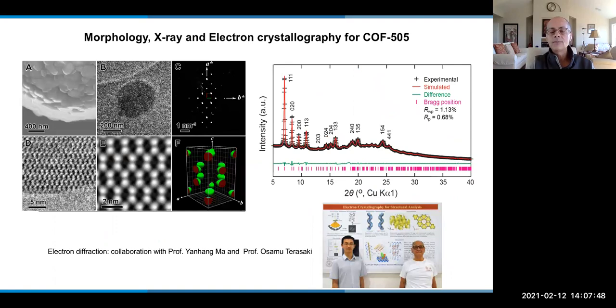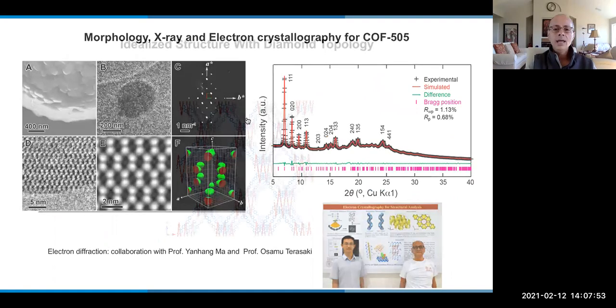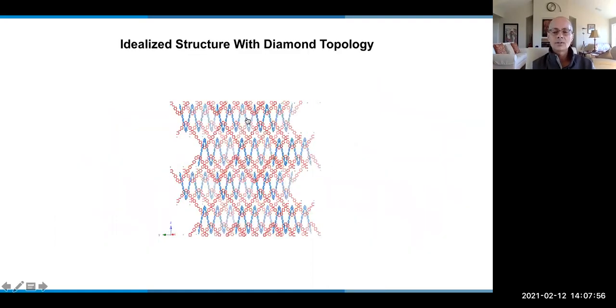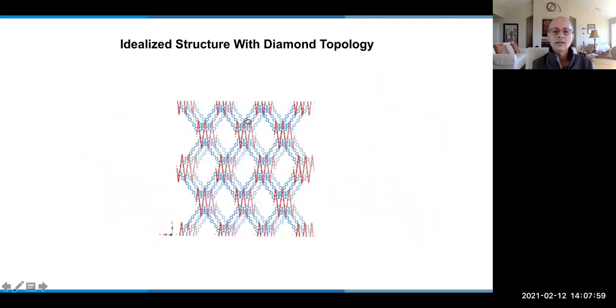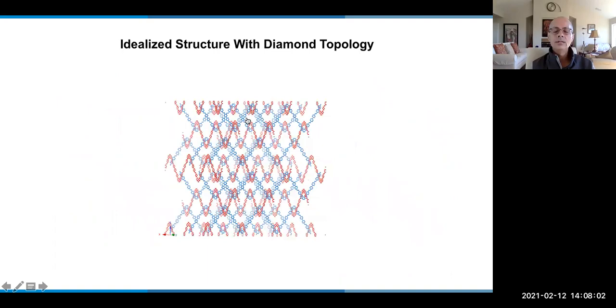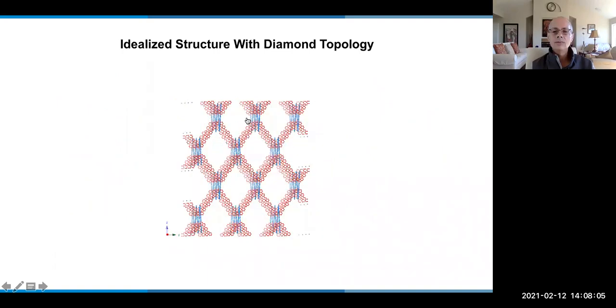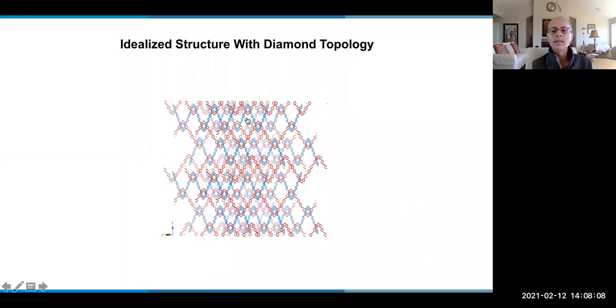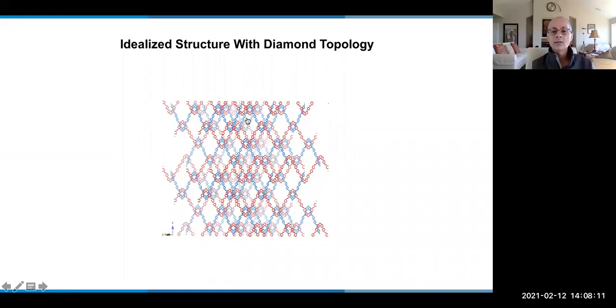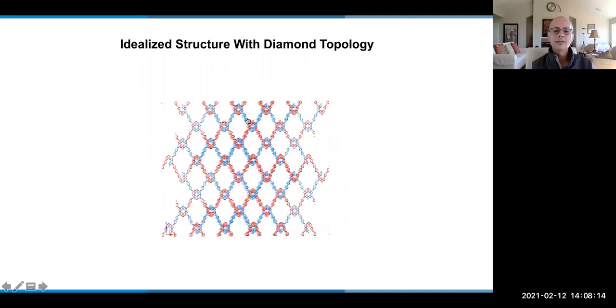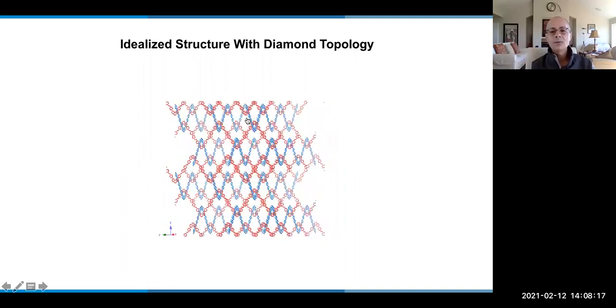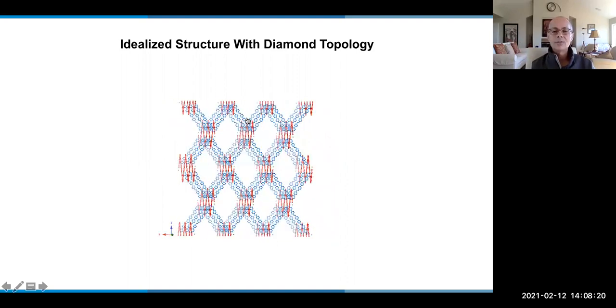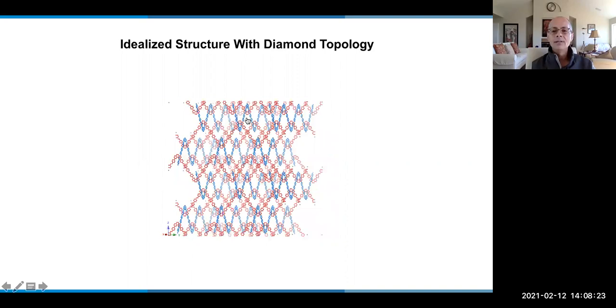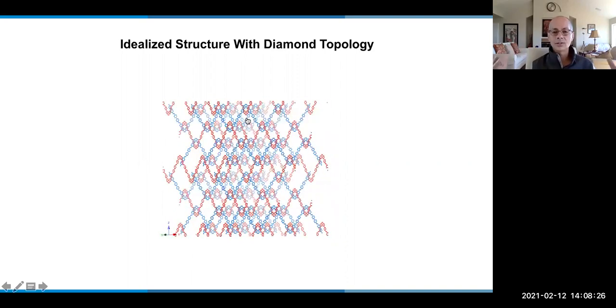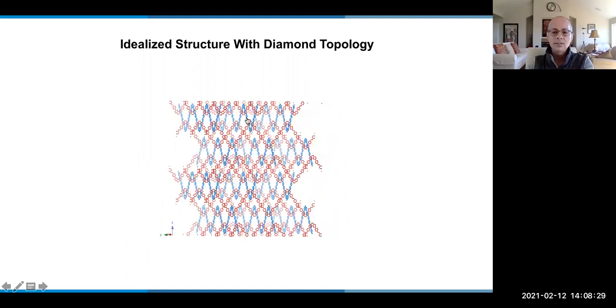It's a highly crystalline structure. We characterized it using electron diffraction and powder X-ray diffraction. And you're looking at an idealized form of the structure. Just for clarity, you can see the blue threads and the red threads interlacing, weaving in and out of each other to make a physically connected structure through physically connected threads. So from a chemist's point of view, this is a one-dimensional structure because it's made from one-dimensional building units that are physically linked. But of course, the overall structure is a woven three-dimensional form.